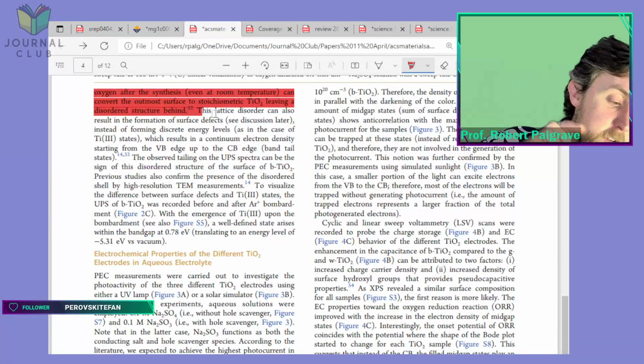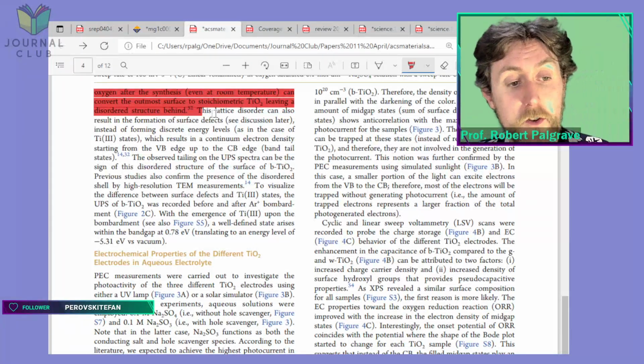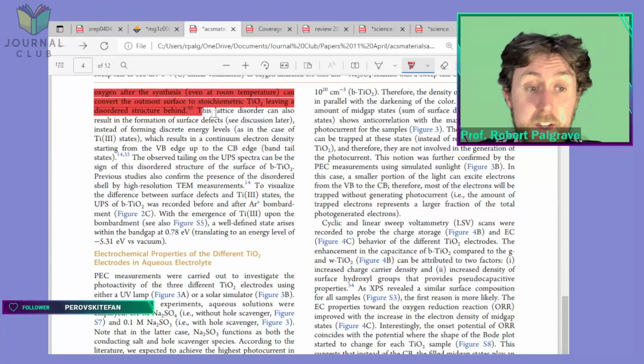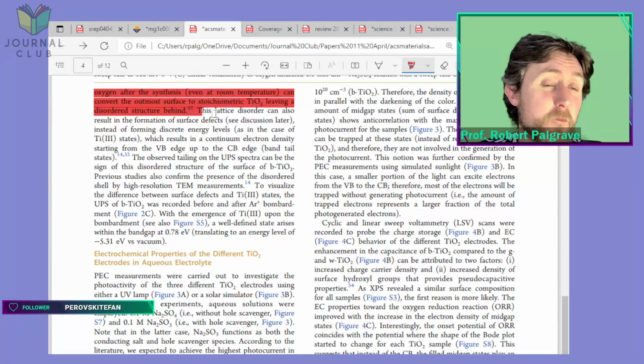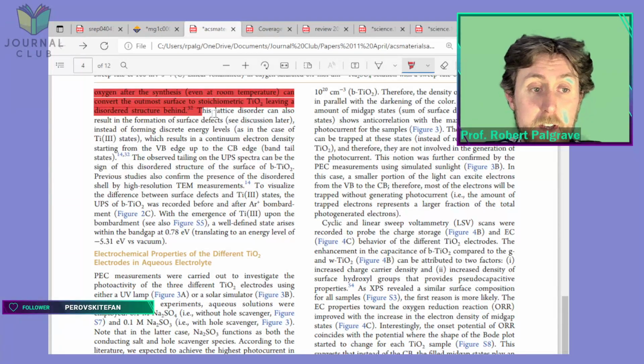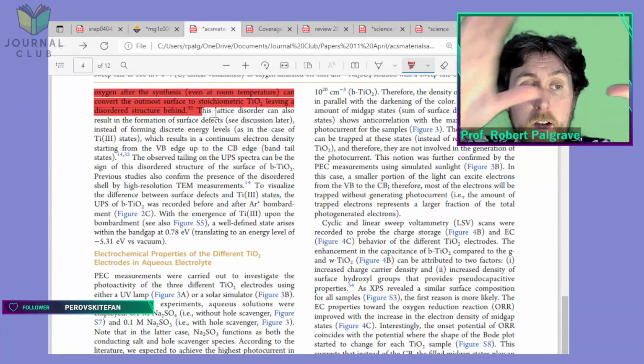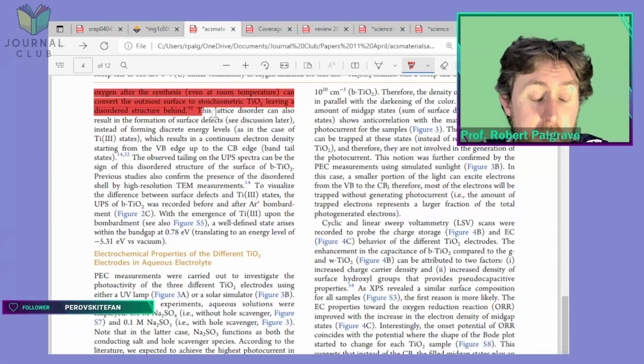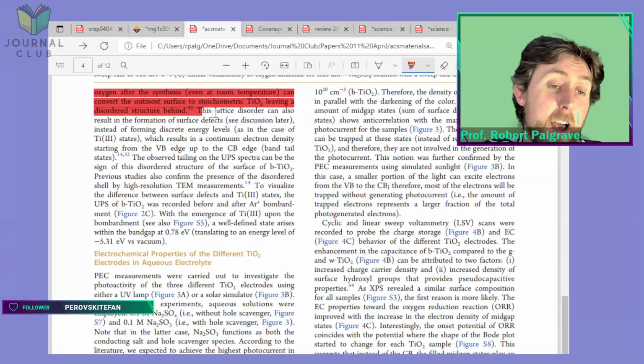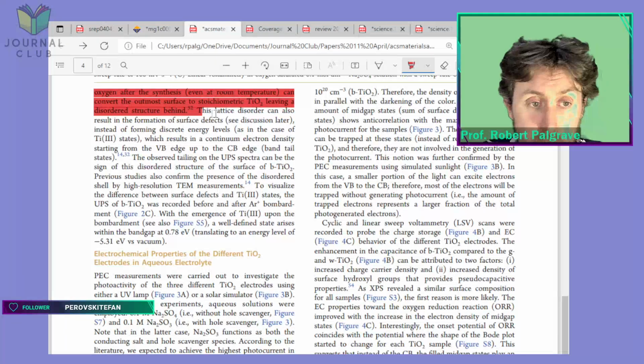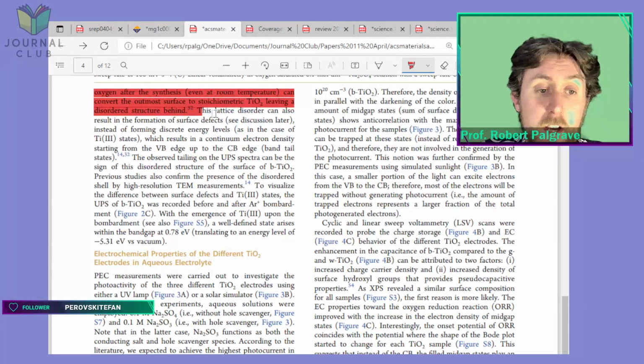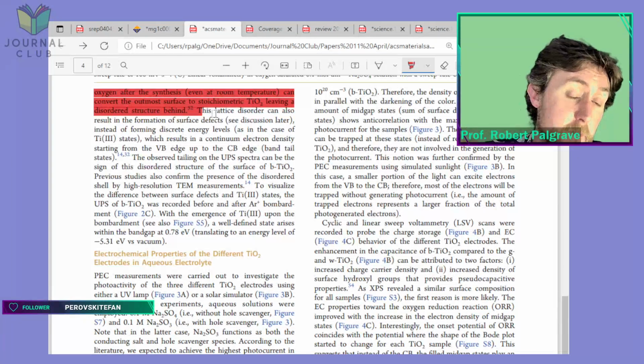So it's buried too deep for the XPS to actually be able to detect. Now, as I said before, that means it's probably 5 nanometers-ish inside the material. So you've got a 5 nanometer kind of disordered layer with no Ti3+ or very low amounts, and then deeper inside you have a much higher amount of Ti3+, which you can kind of access through argon sputtering, or